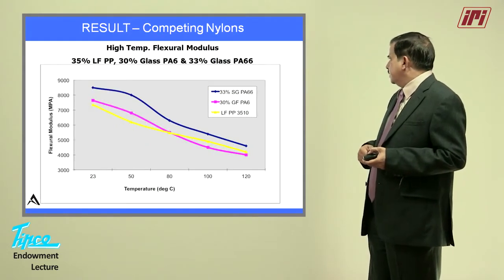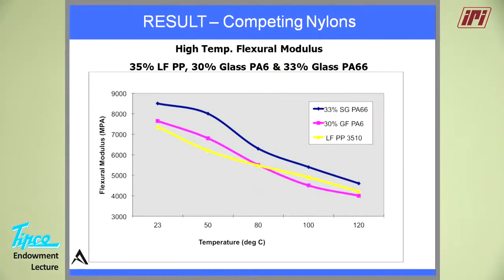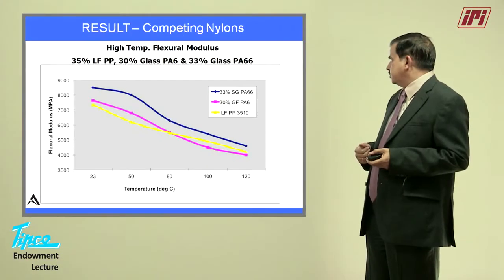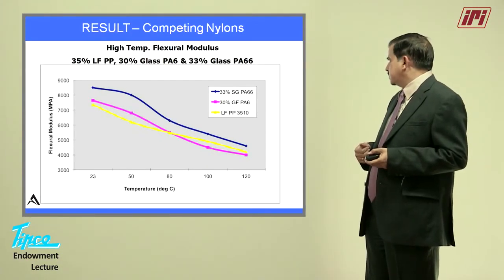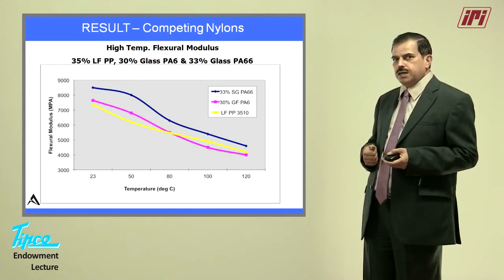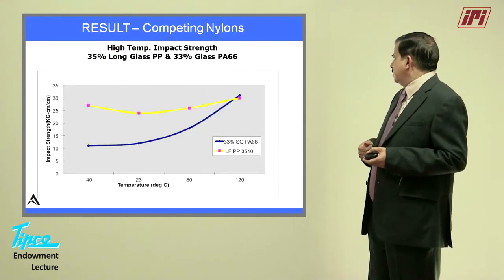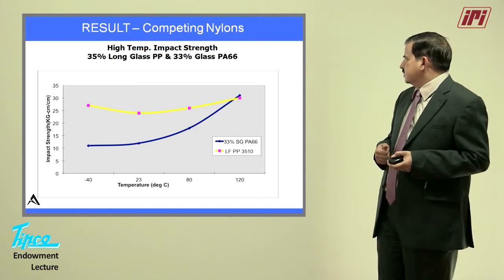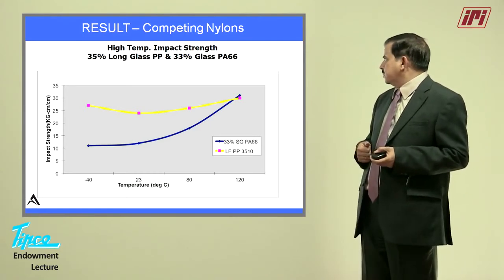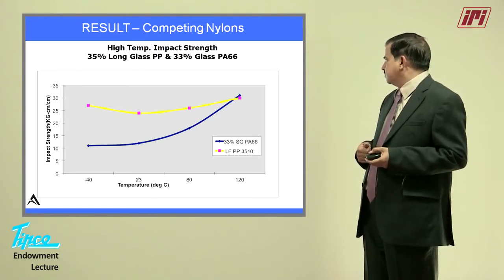Similar is the story with the flexural properties. It lies somewhere in between nylon 6 and nylon 66 up to 120 degrees centigrade. So for most of the underhood applications, 35% long fiber PP can be used as a replacement to nylons. This is a very surprising and good thing about long glass fiber, that